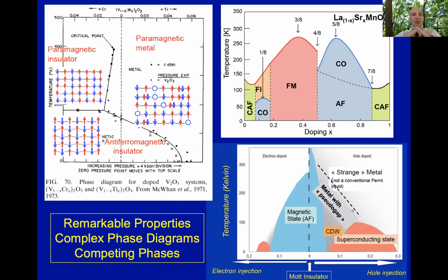So to illustrate this, let me show you in just one slide 3 different phase diagrams of such transition metal oxides, which are all rather old and time-honored examples. Here on the upper left, we see a material that was intensively studied in the 70s, of the past century, 50 years ago, but is still intensively studied in the lab. If you go to the APS March meeting, there are always a few sessions on vanadium oxides, even today. V2O3, or vanadium sesquioxide, which is this material here, is really poised very close to a number of instabilities that cooperate or compete with one another. If you look at these materials under low pressure, actually small negative pressure that you can reach by inserting chromium, although the correspondence between substitution and pressure is to be questioned and has been questioned here.